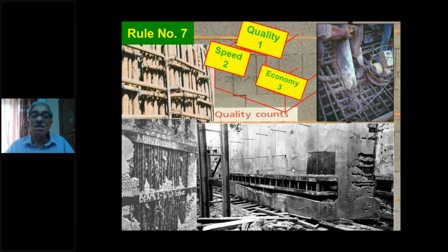Like for example, this particular TG deck, which was cast for unit number 5, had very many defects, and the contractor did not take adequate precautions to pour the concrete. As a result, serious segregation took place, and once the concrete has started, we can't stop it, and this resulted in costly repairs.